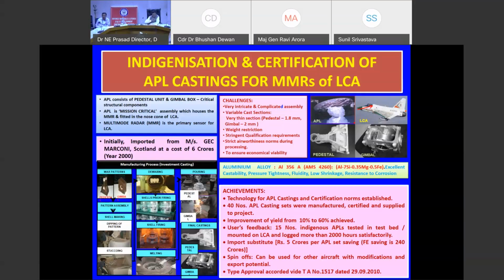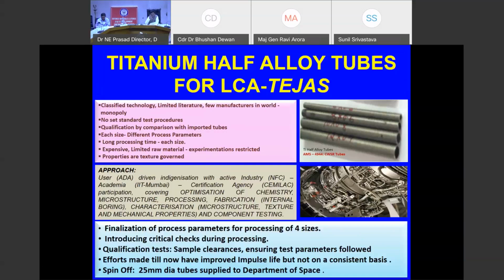Next one. Then we have a very critical half alloy. These are titanium 6 and 4, 6 aluminum and 4 vanadium, a workhorse alloy for titanium, because that is an alpha beta titanium alloy which gives the best of the strength and fracture toughness as well as fatigue properties. But there are special alloys where formability is important, and these tubes will have to have very high impulse loading. That means if you are putting some gas or some fuel or fuel mixture in this, all of that will experience very high frequency fatigue cycle, and such 2 lakh number of cycles, the minimum has to be stood by the entire tubing. If you cut open the aircraft, you can see lot of tubing on the aircraft, and this tubing is done only by 4 or 5 sizes of this titanium half alloy tubes, and very critical to do that.